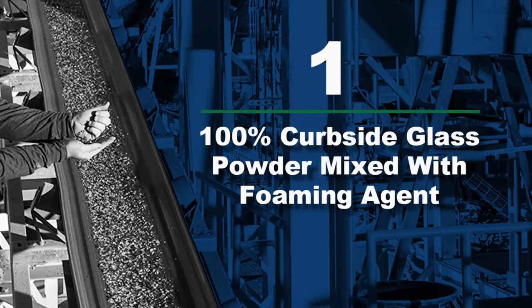All right, so our process to make foam glass aggregate is, number one, we're gonna take that glass powder that we just made, and we're gonna mix it with a foaming agent. And our standard product, which by far is the majority of what we have made in the 5 years that we've been in business, is a closed cell product that we make using a foaming agent called silicon carbide, also known as SiC for short. It's also a recycled mineral from another industrial process. But in this first step, we're basically just mixing the two powders together. It's about 99% glass powder and about 1% by weight of our foaming agent.